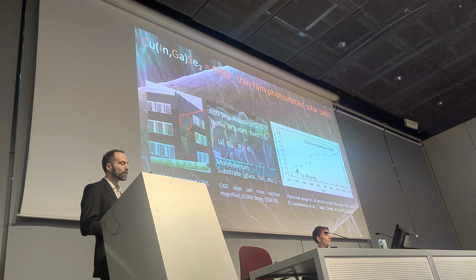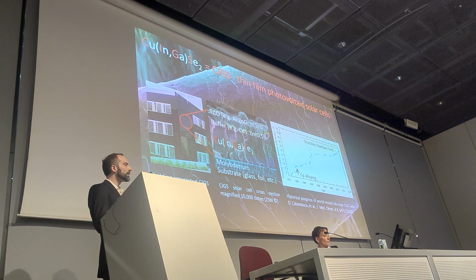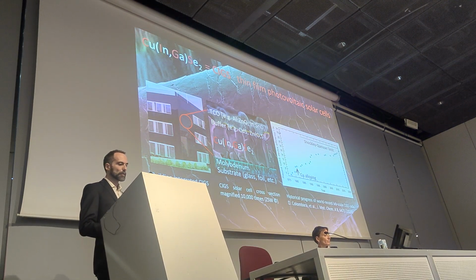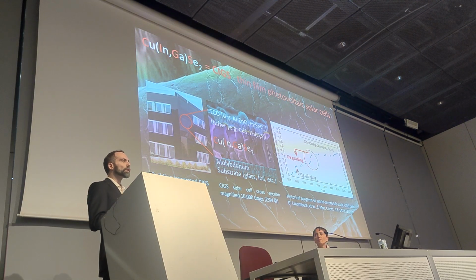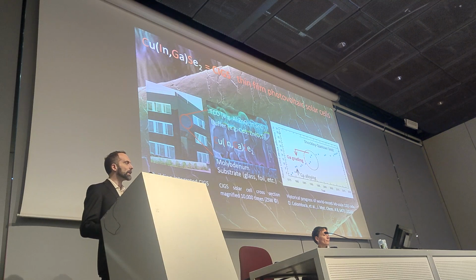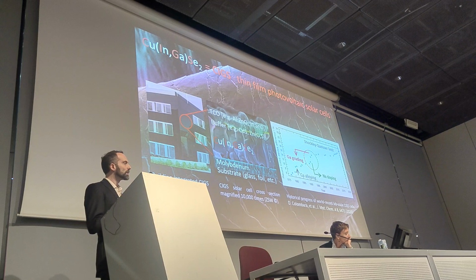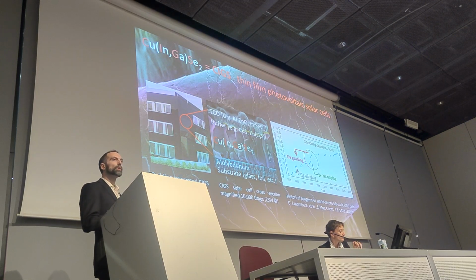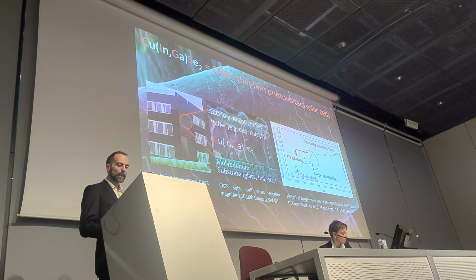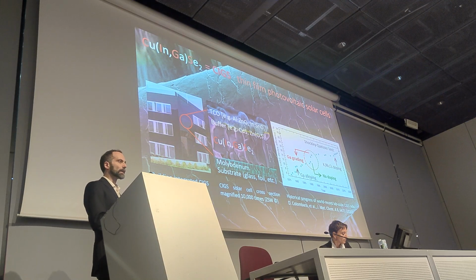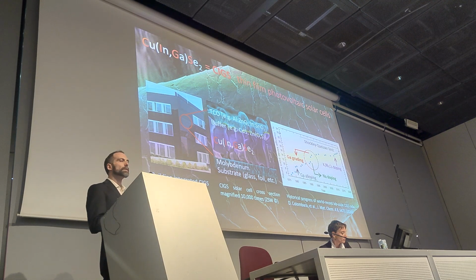Here is a brief overview of the historical progress of the technology. We can identify some milestones, for example, the gallium alloying, and then people started to engineer the distribution of gallium through the depth of the film to minimize recombination at the back interface. And this happened in 1993. And the very same year, another serendipitous discovery was made. People realized that by growing the material on glass, they were able to improve the performance enormously. And later on, people started to introduce heavier alkali metals, potassium, rubidium, and cesium, and this pushed the efficiency of the technology up to 23%.